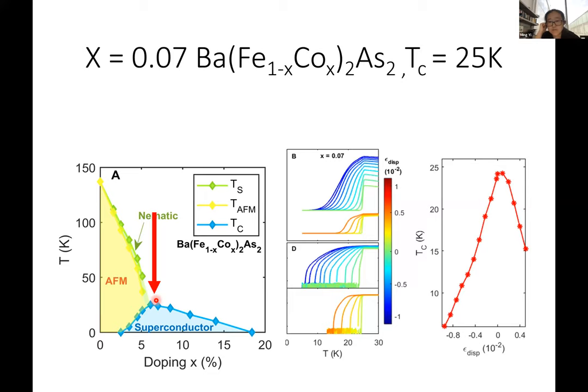Right. So you mean the strain in those cases doesn't enhance the spin fluctuations? Spin fluctuation actually enhances. We have actually shown that when you put pressure on, your nematic anisotropy actually changes. Spin fluctuation actually changes, shifting more from the one side to the other. So there's a direct coupling, yeah. But then you don't see any effect on Tc. Tc also changes. It's always coupled, right? But the amount of strain we can apply is rather small, so the Tc changes are small.